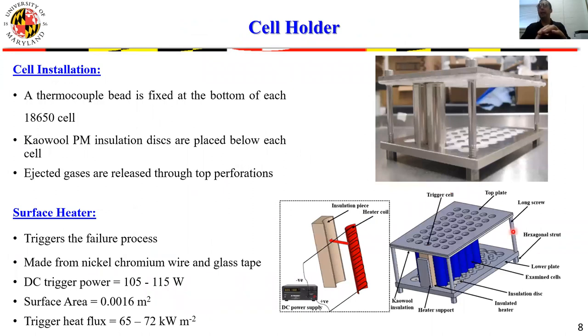Our simulated battery pack, a simulated battery module, I would say more accurately, looks qualitatively like this. For most of the experiments that we performed, we took a 3x4, 18650 cell array. 18650 cells are cells that are about the size of a human finger. And we put them together in a tightly packed configuration, and we initiated failure in one cell, which we call the trigger cell, through a localized heating. And then we looked at the propagation of this thermal runaway through the rest of the cells by monitoring their temperature at the bottom of individual cells.